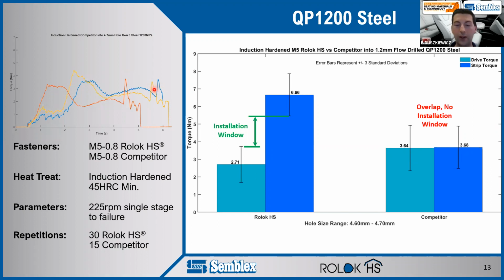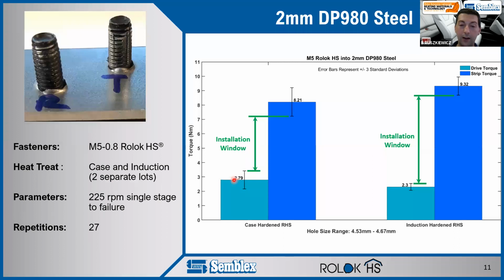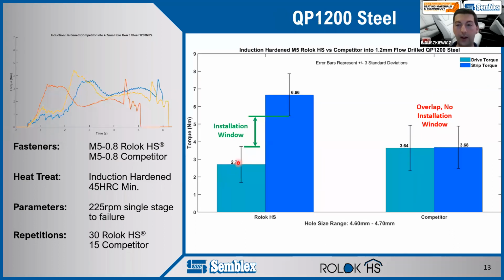When we transition over to Rolok HS, we do see a window across the hole size range. It's not as large as we would like, but that's why we're starting to look at some other heat treatments. What's interesting is that in this steel, our drive torque is pretty good. It's almost the same as it was in DP980. Our DP980 was about 2.8, and it's a little bit thicker steel. Right here, 2.7, so about where we'd expect to be. We're likely not taking very much lead thread damage here at all. We're probably getting some, which is why we have this larger variation, but we're still able to drive in.